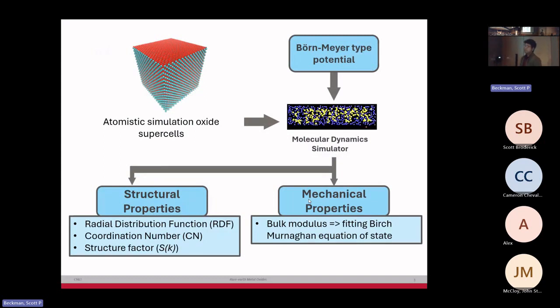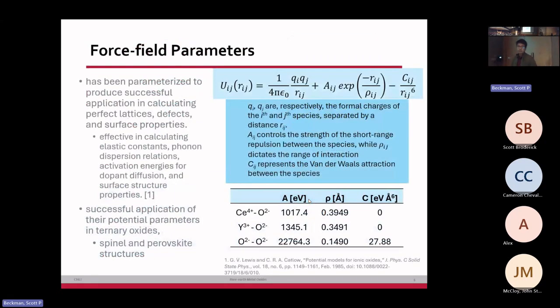We have also analyzed some mechanical properties using molecular dynamics. For example, we calculated the bulk modulus and fitted the bulk modulus against the Birch-Murnaghan equation of state. For the force field parameter, we used Born-Mayer potential which has been successfully used for crystalline solids or oxides of different binary and ternary compositions.